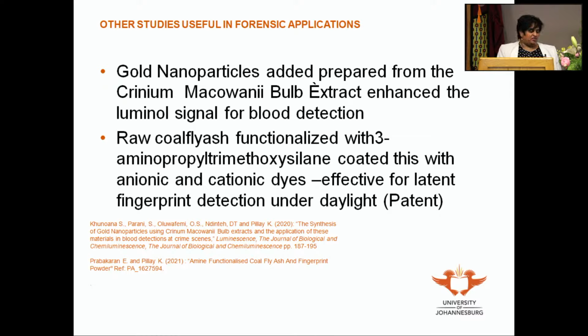And then further to the other work which we've performed on latent fingerprint detection, we also took waste coal fly ash, modified it with functional groups and coated dyes onto this. And we found that it was effective for latent fingerprint detection under daylight conditions. And this is something that law enforcement officials are really looking for because nobody wants to go out at night and shine a UV lamp just to find fingerprints. So this is certainly a material that could make the lives of law enforcement officials much easier.